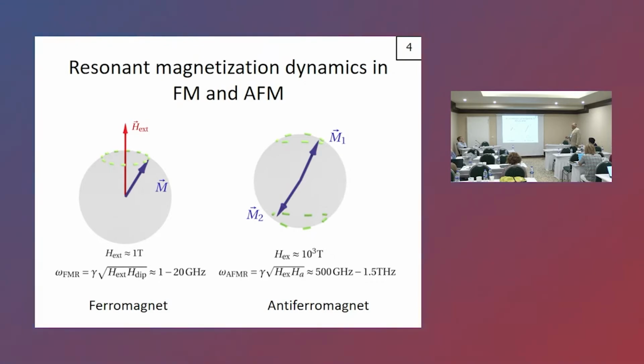Now, if we want to actually create a generator, we need to somehow excite this eigenmode either in a ferromagnet or in an antiferromagnet. In a ferromagnet, you can do the following. You can create a spin polarized current where the vector of polarization is parallel to the magnetization, and with a certain direction of the polarization, that will create an anti-damping torque, which will try to destabilize the static direction of magnetization, which in a static case is simply parallel to the external field.